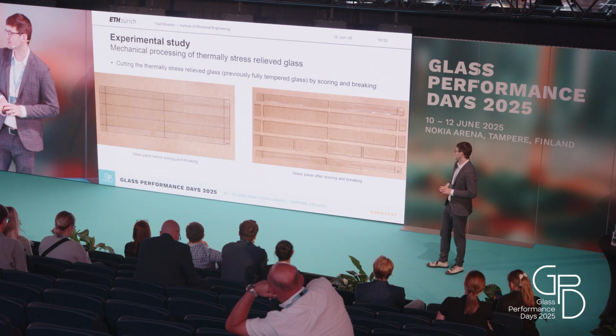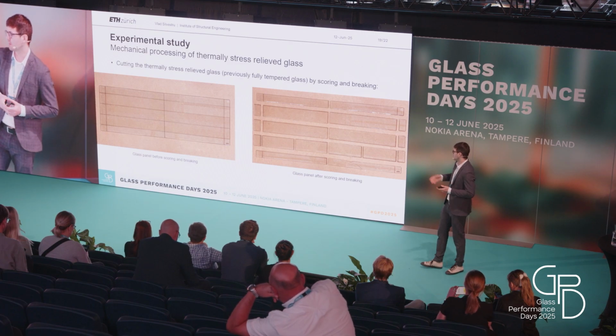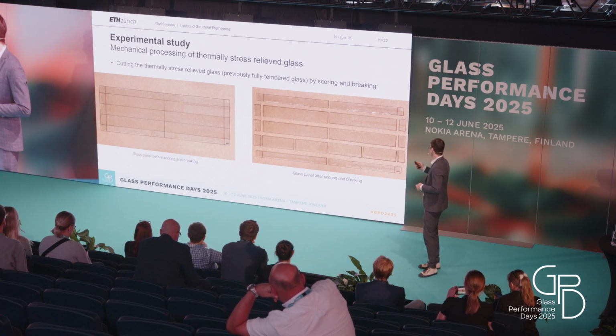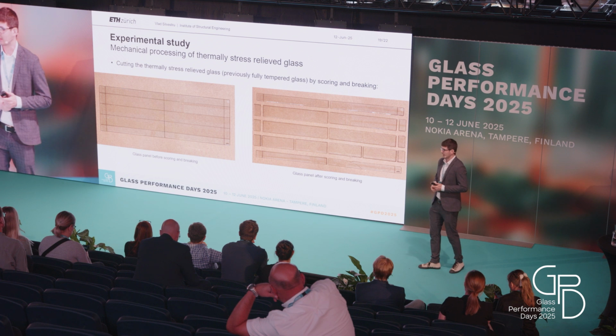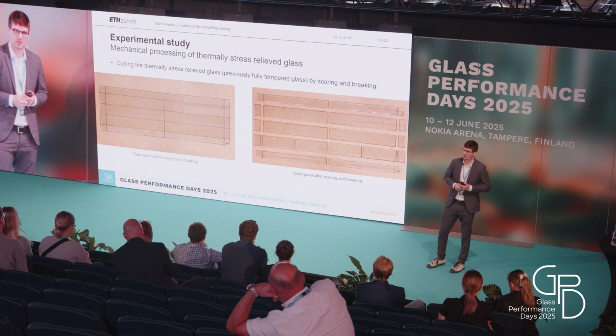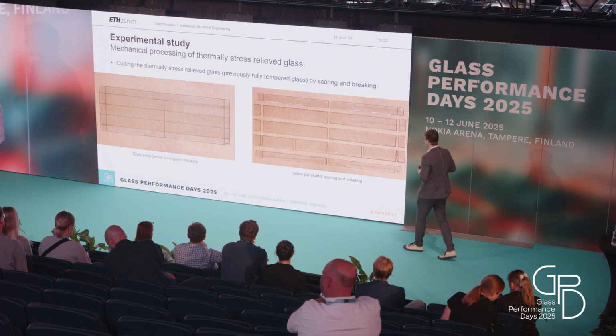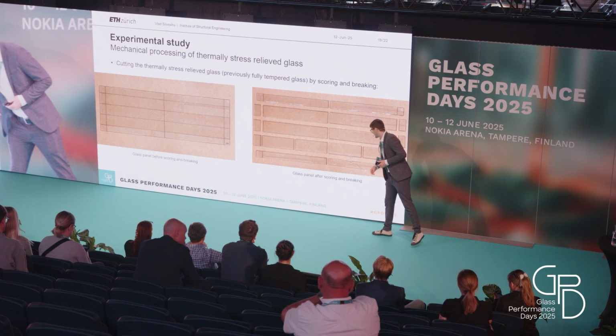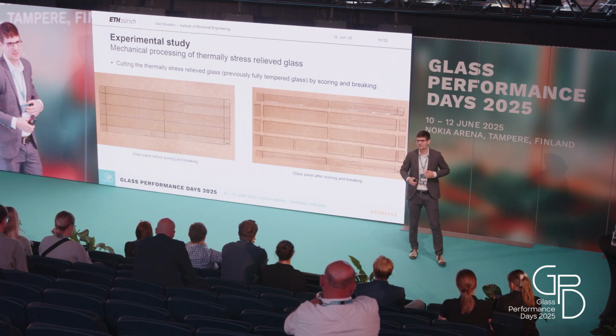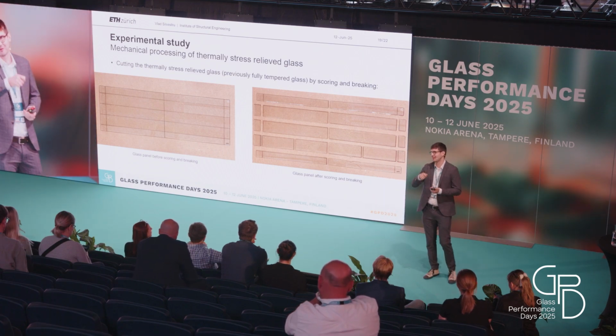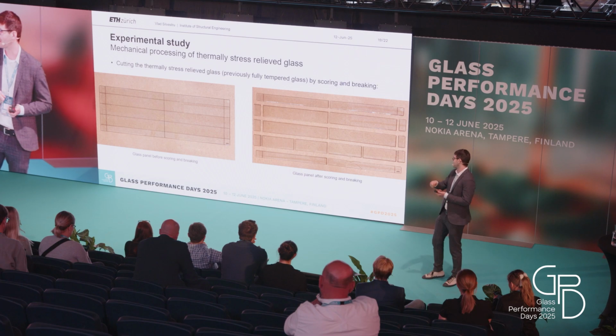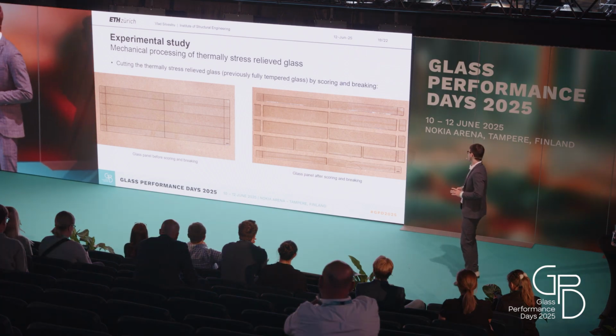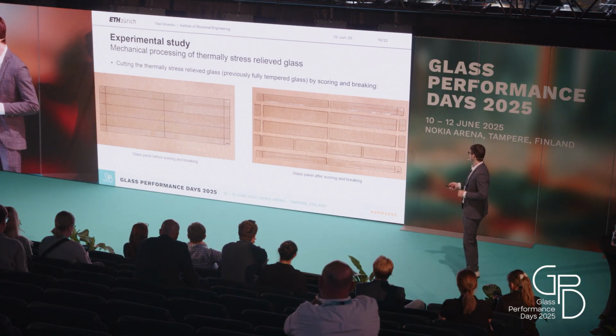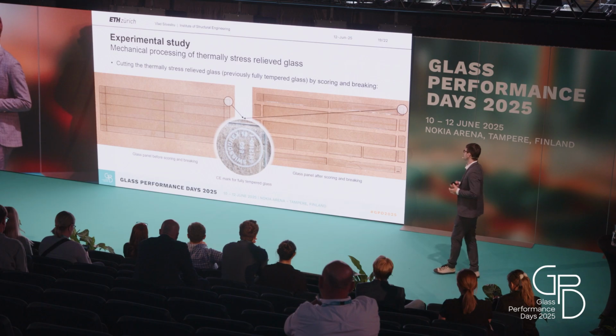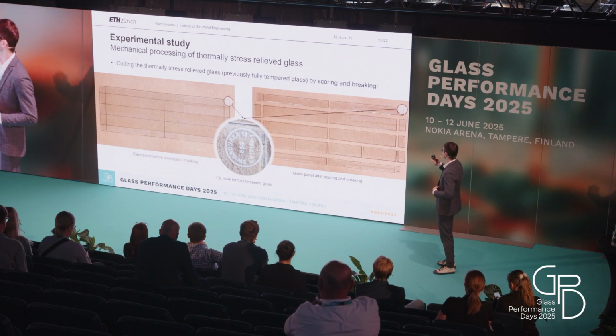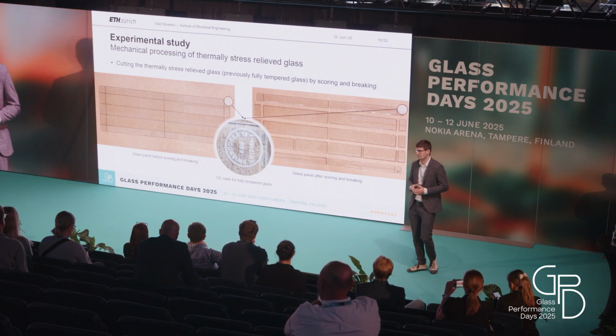And here is a panel before cutting, so before scoring and breaking, and afterwards. It worked pretty well. The damage that you can see here is mainly because of my poor skills in scoring. The first scoring lines that I made, the oil glass cutter just slipped on the glass. And you can see in the corner, even after the treatment, the CE mark for the fully tempered glass is